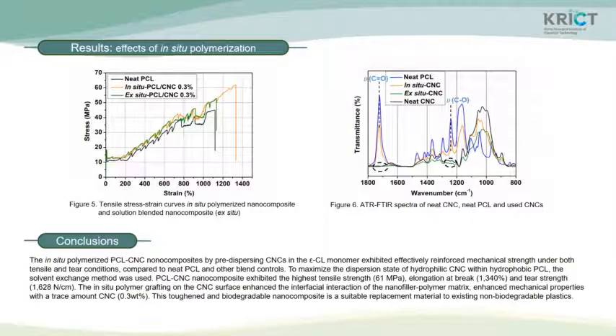During the in situ polymerization of PCL with CNC, we expected the CNC nanofiller interacts more with the polymer matrix through chemical modification of CNC surface than ex situ approach. In figure 5, we can see the toughening effect is much more noticeable in the in situ method than that in the post-blending method, probably because the higher dispersibility maximizes the toughening effect of CNCs.